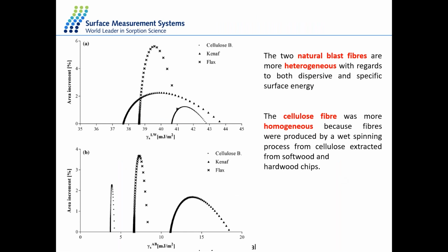We have then carried out surface energy experiments. We can see that the 2 natural fibers have much broader peaks, so we have higher heterogeneity. In this case, we're looking at our specific surface energy and also the dispersive surface energy. When we're looking at specific surface energy, we can again see that the synthetic cellulose fiber is more homogeneous, with a narrower peak. This is because of the way it was produced and processed synthetically in a controlled environment. So it's very interesting to understand what the IGC instrument can help you do to understand your material.